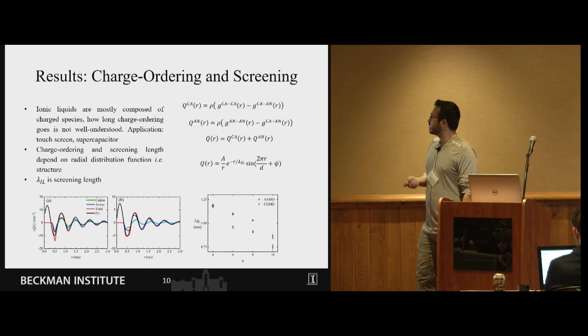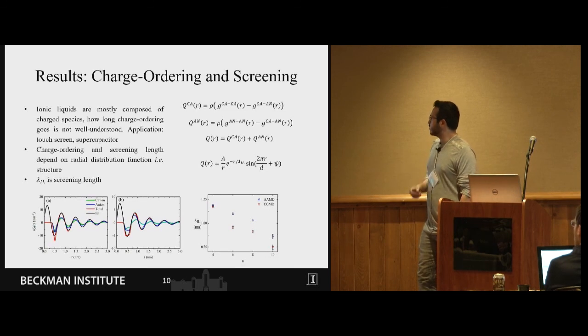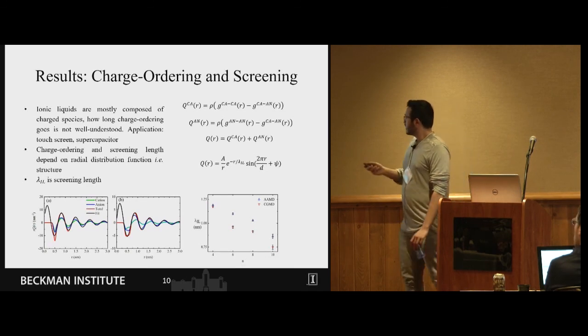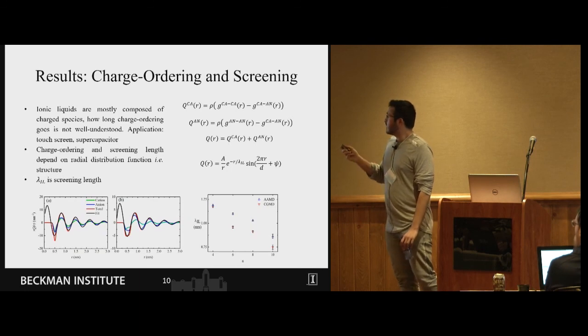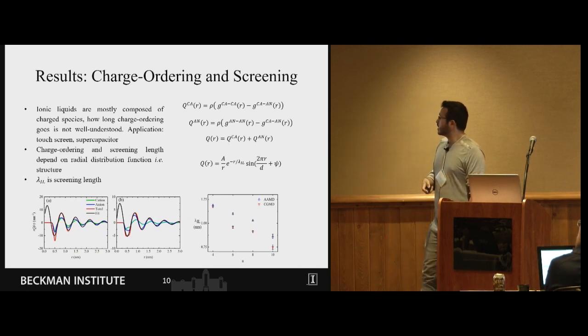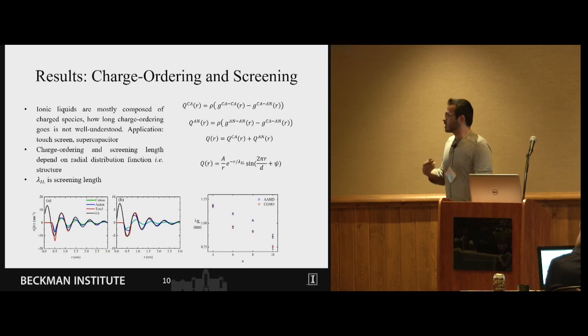This is kind of close to what they mentioned in the literature and shows that these liquids interact for a really long range compared to their liquid phase. Furthermore we calculated these screening lengths for different alkyl chain lengths and we show that by increasing the number of alkyl chain lengths the screening length decreases and we give some idea why it is the case.